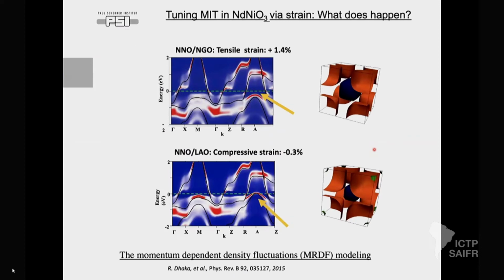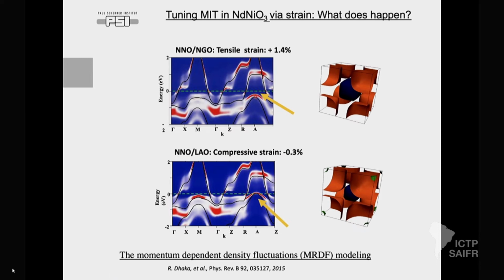In order to understand what we are seeing, we need calculations. Our collaborators calculated that, and what we got is a very good agreement with the experiment. This band, which is hole-like at the A point, stays pretty much below the Fermi energy, about 200 to 300 millielectron volts below, when you have tensile strain. Once the system is compressively strained, it crosses the Fermi energy and forms the new Fermi surfaces. Besides that, there is also a change of the kF position of that band. This momentum-dependent density fluctuation calculation shows very good agreement and explanation for this alteration and modification of the Fermi surface. So this is the new pocket, which is now at the zone boundary.